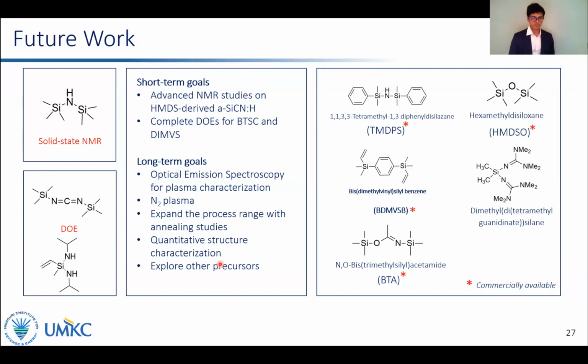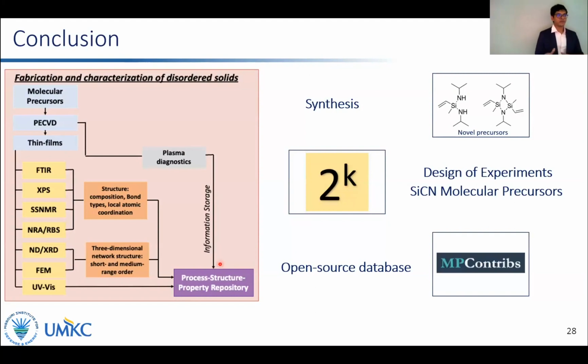To close the loop with my dissertation objectives, we successfully fabricated molecular precursor-derived amorphous hydrogenated silicon carbonitride as a class of complex disordered solids. While doing so, we understood the process-structure-property correlations and developed the process-structure-property database. Some notable contributions from this work include the synthesis of novel precursors and adopting factorial design of experiments to study a-SiCN molecular precursors, understanding their process-structure-property relations, and contributing the experimental data on PECVD derived materials to MP Contribs.